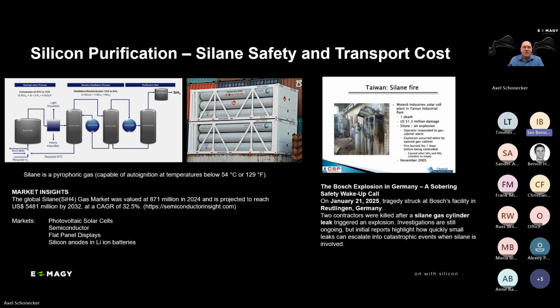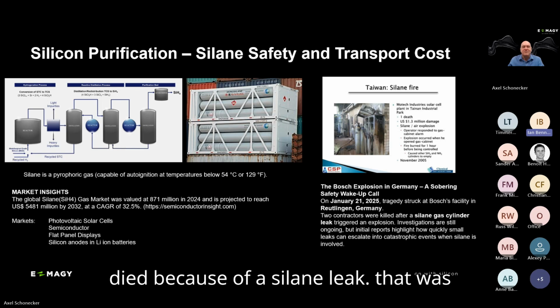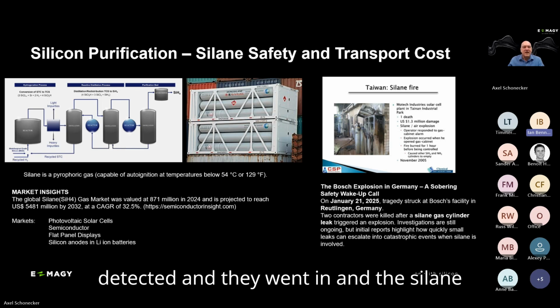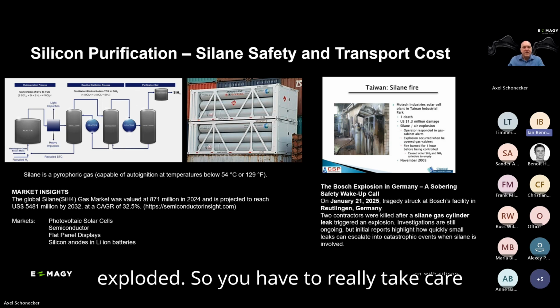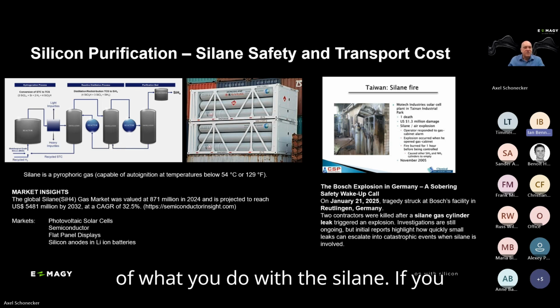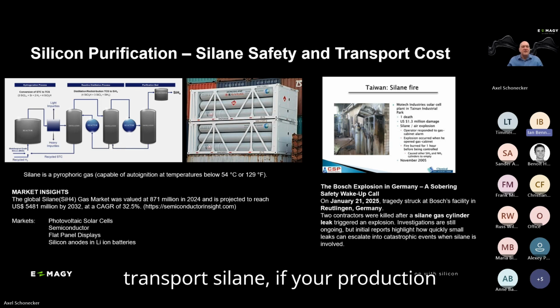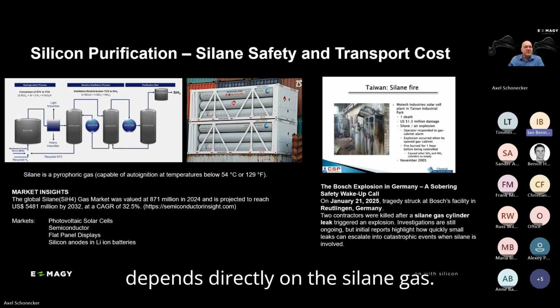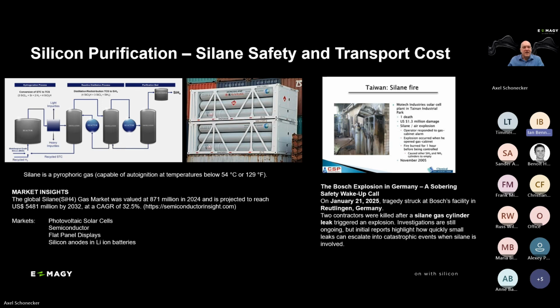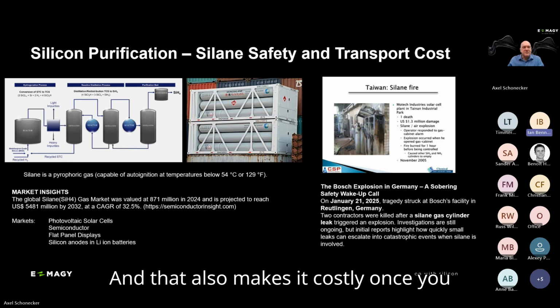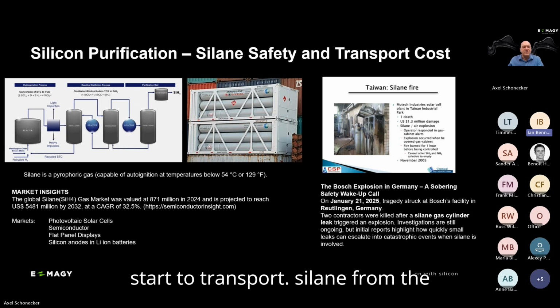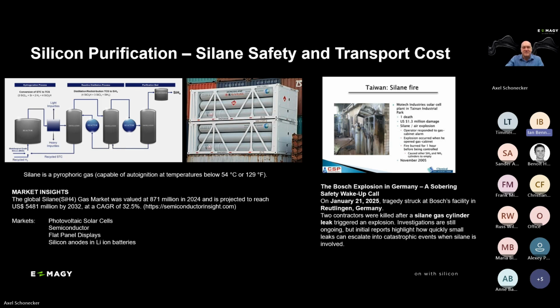In Germany, earlier this year, 2 people actually died because of a silane leak that was detected, and they went in and the silane exploded. So you have to really take care of what you do with the silane, if you transport silane, if your production depends directly on the silane gas. That also makes it costly once you start to transport silane from the silane plant to some other places.